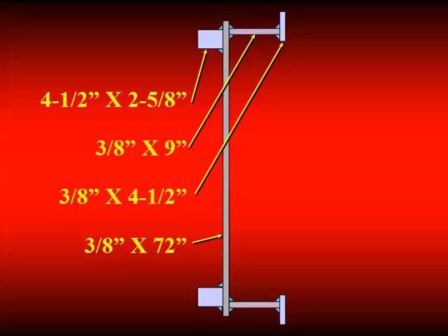This is about full scale on the screen. This is 72 inches deep. 10 welds on here. The center of gravity of the 10 welds is here. The neutral axis of the section is here, and they're displaced by 2.39 inches. Without thinking about this, 150 feet long, the fabricator tacked everything together and put in the 10 welds and had a 150-foot long banana because it took a great swing to the right. And you can all see why that would happen, right?